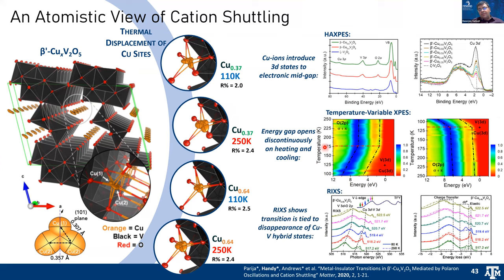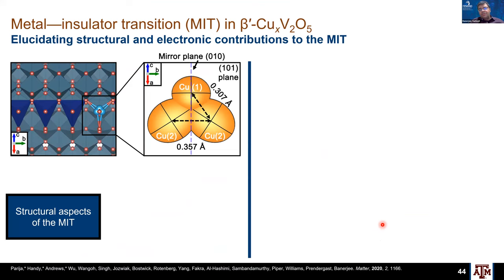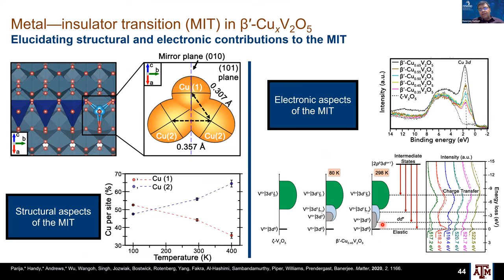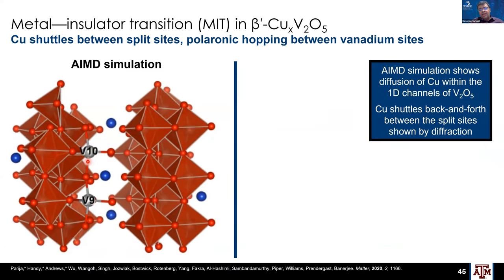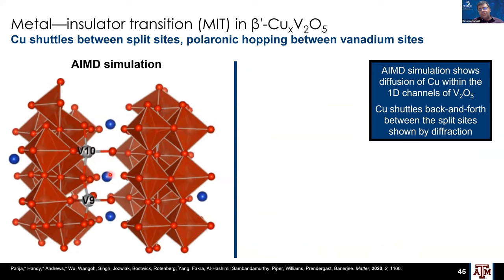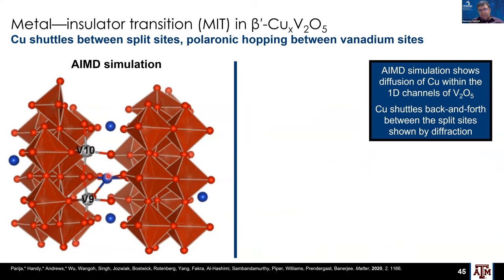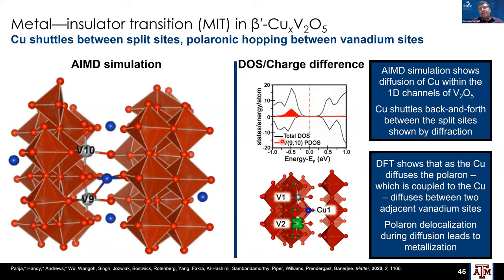This is some photoemission spectroscopy at the ALS and some RIXS also done at the ALS that really shows some of the more detailed aspects of the transformation, and the copper occupancy changes as a function of temperature. And this is a quick AIMD simulation. The structural distortion is very, very small. Copper, instead of being localized on one site, spreads out across two sites, and that induces a very large electronic transition once you've got enough of this. And depending on how much copper you have in the structure, the transformation temperature is tunable.